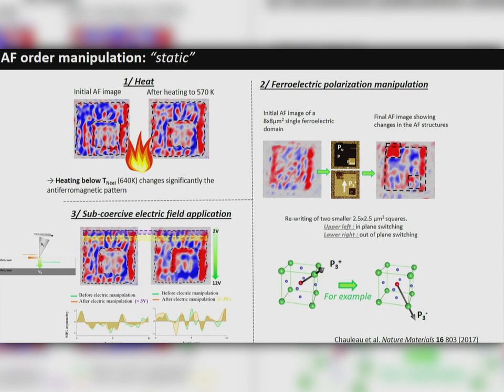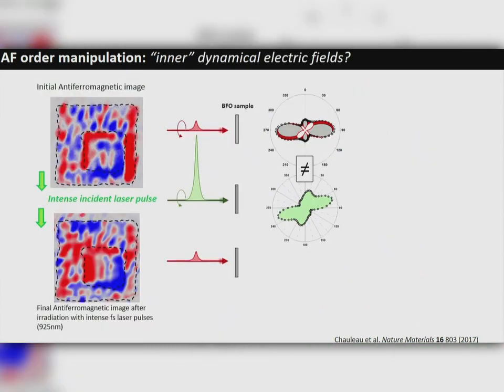What is very interesting here is a subcoercive change of antiferromagnetic domain. So that means we don't only need to move the polarization, we can apply only a small electric field. This is what is interesting. But the last thing is that what we've noticed is that by increasing the intensity of the light quite a lot, we have changed the whole pattern of the antiferromagnetic domains. And if we did that while applying very, very intense light, then we can even see that the angular dependence was fully changing.